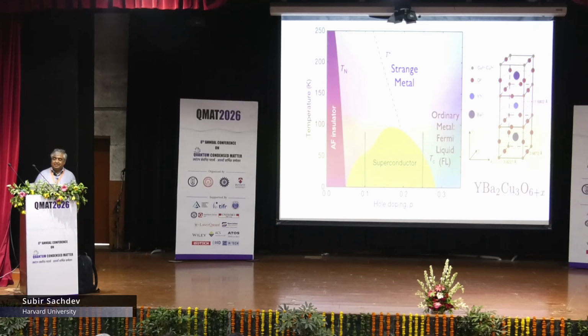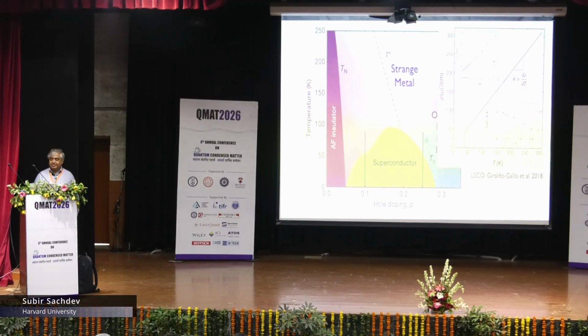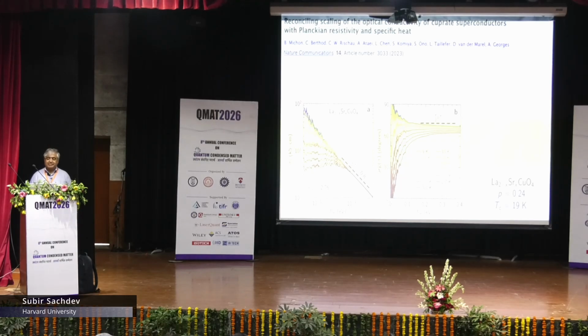Okay, so why doesn't it apply? Well, the most famous law is the linear dependence of the resistivity on temperature over a very long temperature range. And we saw several talks today talking about that in twisted bilayer graphene. But really, the resistivity is kind of hard to interpret because it's theoretically a very difficult quantity to calculate properly. But a much nicer quantity is something you can get from the optical conductivity. So this is data obtained from the infrared light reflectivity of this material. You're measuring the conductivity, sigma of omega, here, as a function of frequency of light. So these are the phase and magnitude.